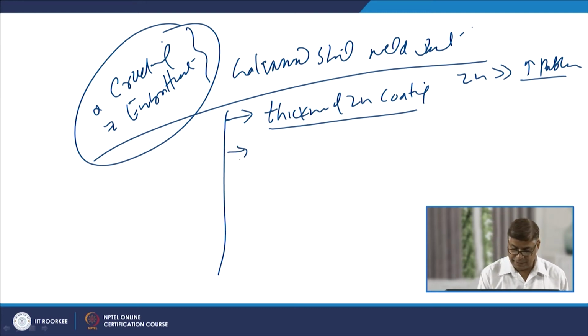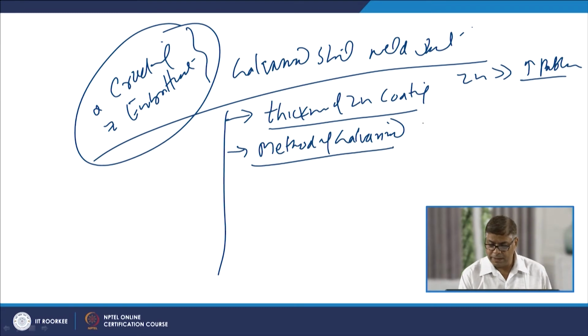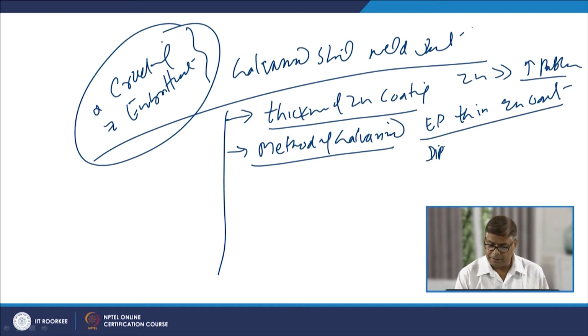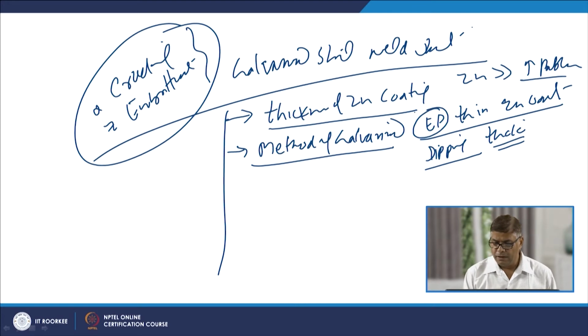Next is the method of galvanizing. We know that electroplating results in a very thin zinc coating as compared to hot dipping, where we get a very thick coating. So, the galvanized steels produced by electroplating lead to lesser problems associated with cracking and embrittlement, due to the lower content of zinc in the weld metal contributed by the zinc coating, as compared to the case of the galvanized steel sheets produced by the hot dipping method.